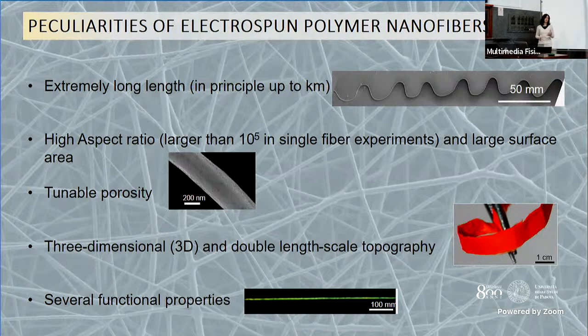So they are particularly interesting for applications in fields such as sensing or filtration, where with such a large surface area you can increase the sensitivity of your device a lot. Also, you can decorate the surface of the fiber. For example, they can be porous on the surface, or you can decorate them with nanoparticles or protrusions on their surface, again increasing the surface area. Then, as you have seen before, and as you can also see here, they have an intrinsic three-dimensional character. So these are objects that you can handle very easily. But when you handle them, you have to remember that they are made of nanomaterials. So they are an ensemble of nanomaterials, and we have a double length scale topography in this sense.